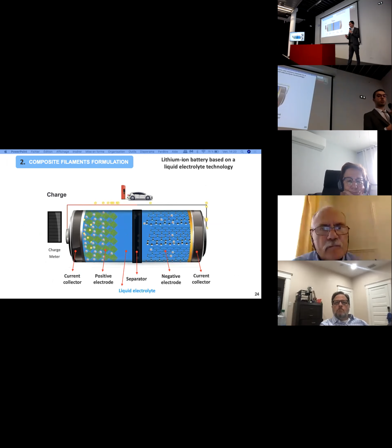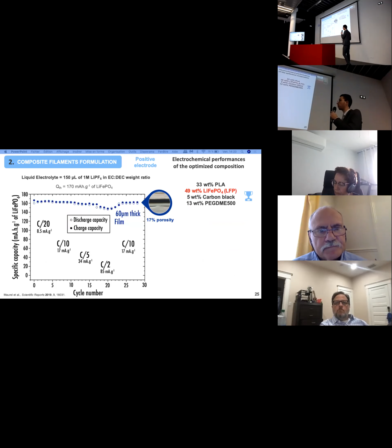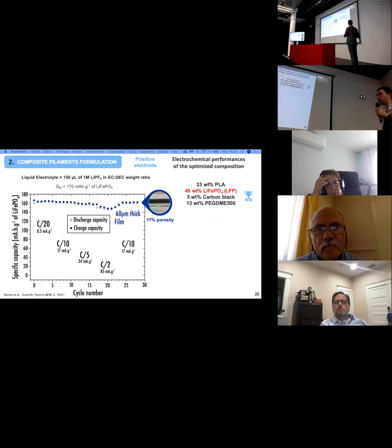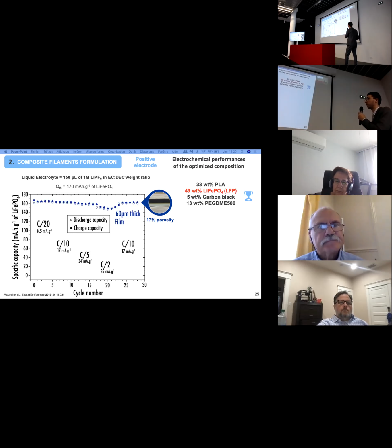So I just mentioned the negative electrode, but actually we did exactly the same work focused on the positive electrodes. I will not go into details right now because it's exactly the same, but I just wanted to show you the electrochemical performances. Here again, with the optimized composition, we were almost reaching the theoretical capacity of lithium iron phosphate in this case, which is about 170 milliampere hours per gram.